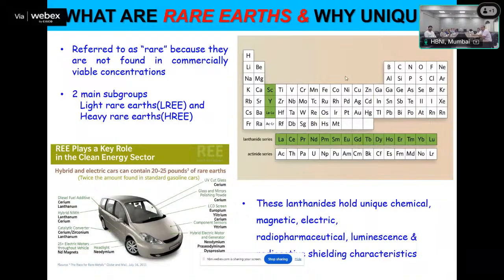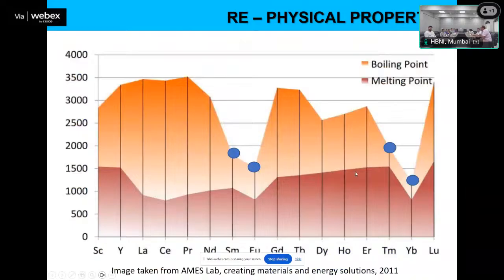But there is an issue with four metals: samarium, europium, thulium, and ytterbium. These four cannot be obtained by simple molten salt electrolysis, or you can say by making fluoride or chloride and treating with calcium. That will not work, because the reason for this low boiling point is that these are divalent and trivalent, two states exist, and one tries to get a complete full shell or a half-filled f shell. This is the factor that contributes. It has +2 and +3 oxidation states.